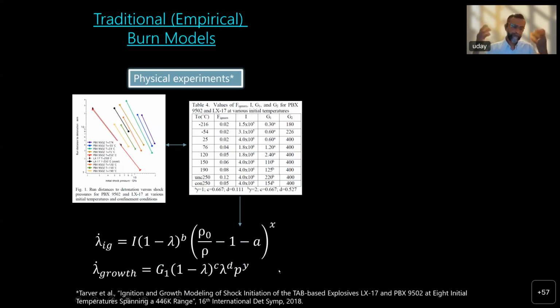Now, this has been for a very, very long time, especially exemplified by the phenomenal work of Craig Tarver and others at Livermore and other labs as well. Typically these phenomena of the hotspot formation and the mesoscale phenomena leading to the macroscale detonation were inserted into hydrocodes by using what are called burn models or reactive burn models. There are many flavors of these, and depending on what your speed is, you can use many of these which are well calibrated for some particular formulations of energetic materials. But a common or popular one is from Craig Tarver and others, Tarver, Nichols, a lot of people at Livermore contributing to this. It's called the ignition and growth model,